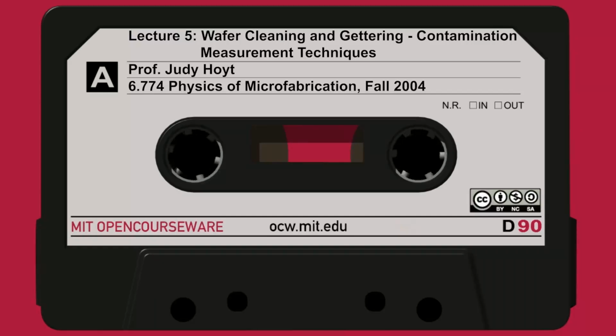Let's say just for comparison, let's look at potassium here. TXRF doesn't measure it very well. The lowest it can measure here is about 20 times 10 to the 10th, or 2 times 10 to the 11th. Not all that sensitive. At least a few years ago, that was the limit. Maybe they've improved it. But look at the detection limit using surface SIMS. It's 0.01 times 10 to the 10th, or 10 to the 8th per square centimeter. Much more sensitive. So it gives you an idea of what the detection limit is. So if I know that I'm concerned about potassium, I would shoot for SIMS, not TXRF. So it's a nice quantitative comparison for the different elements.